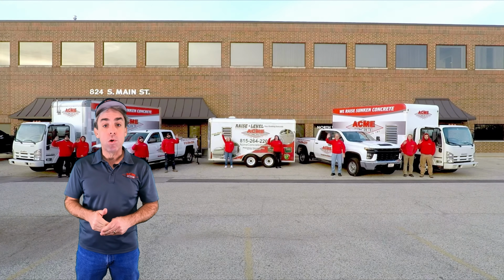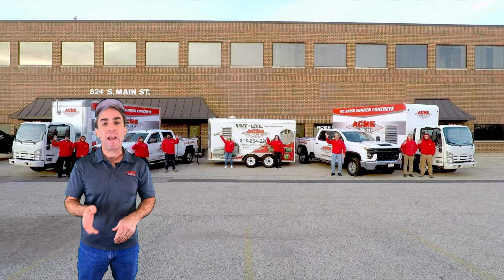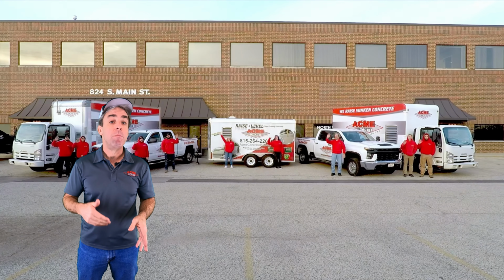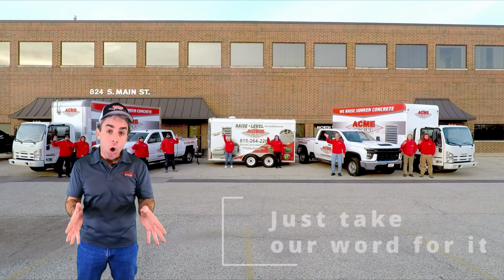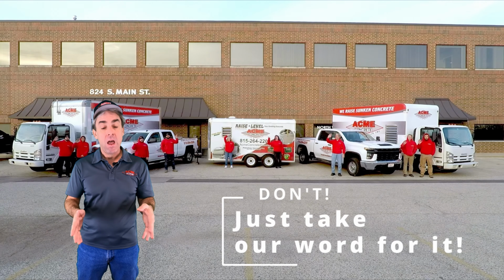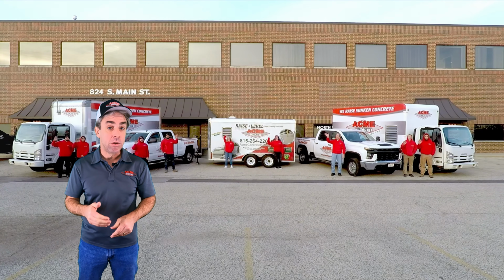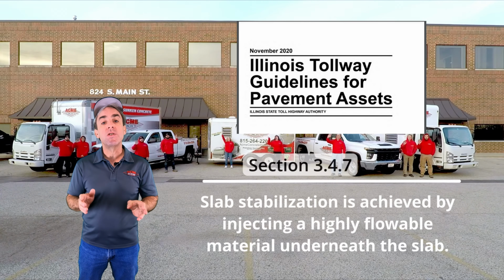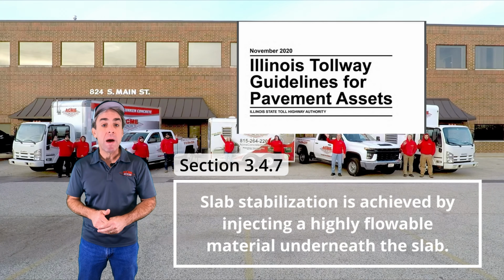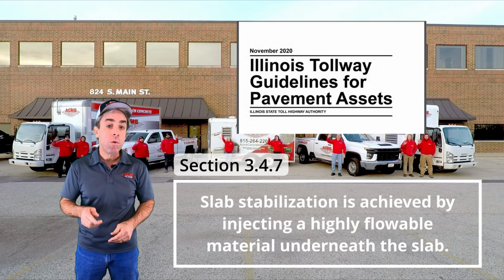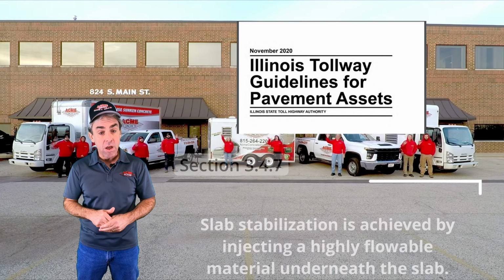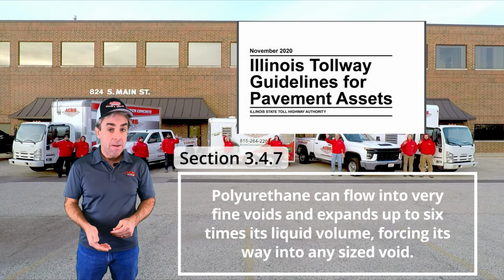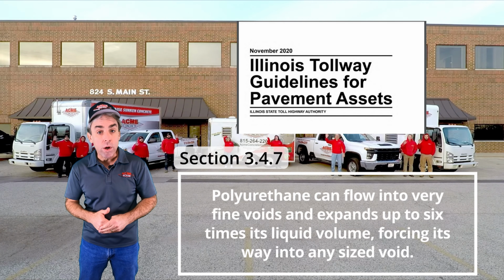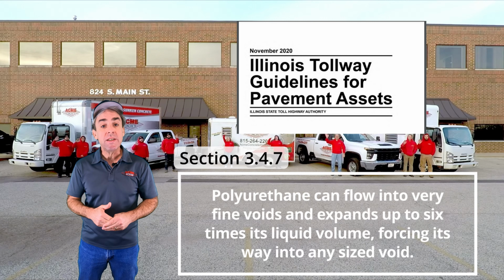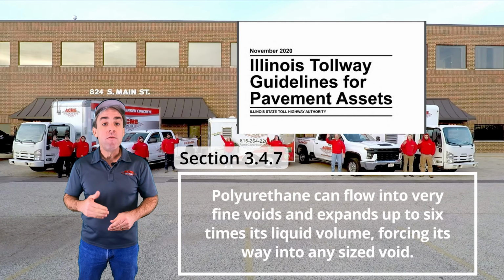Our polyurethane will clearly do a better job than any mudjacking service, but once again, you don't have to take our word for it. Our claims are backed up by the Illinois Tollway, which says slab stabilization is achieved by injecting a highly flowable material underneath the slab. Polyurethane can flow into fine voids and expands up to 6 times its liquid volume, forcing its way into any sized void.